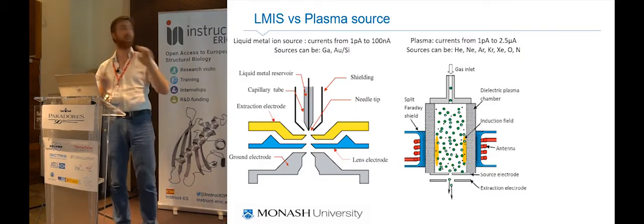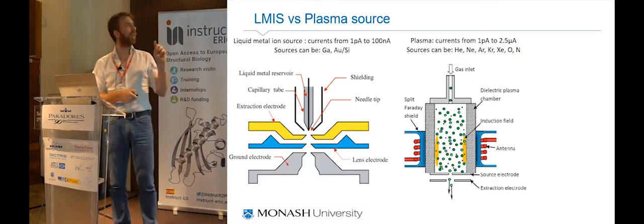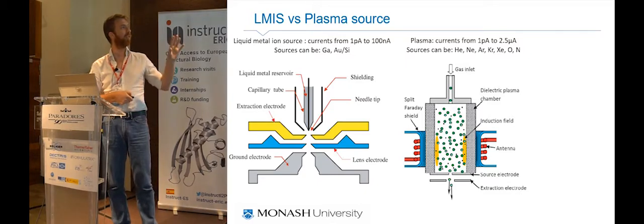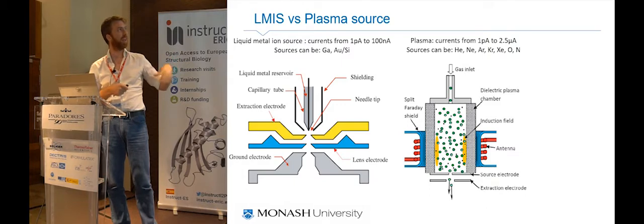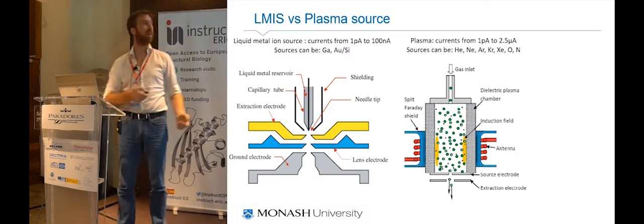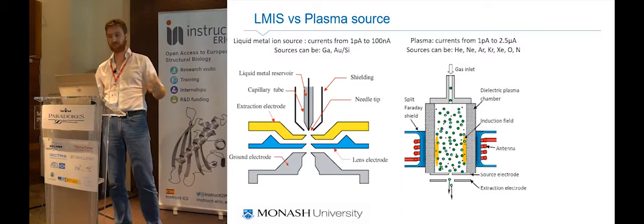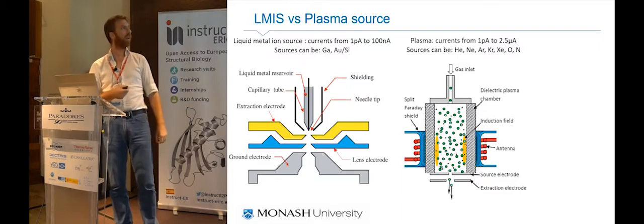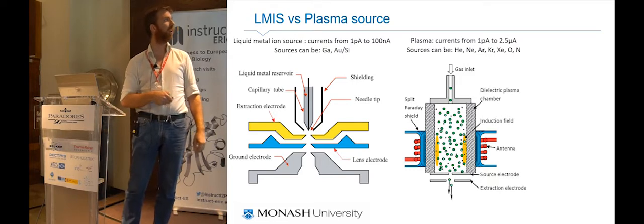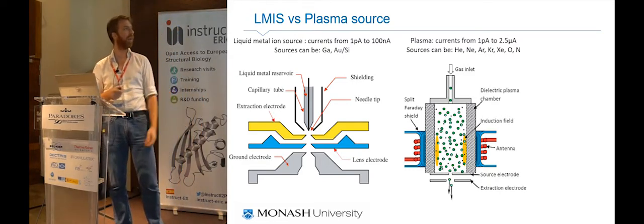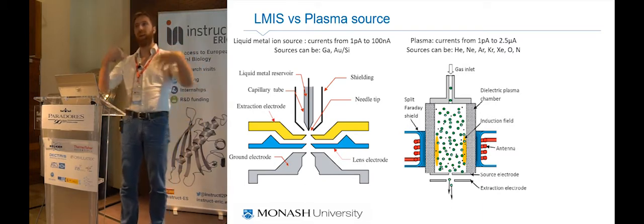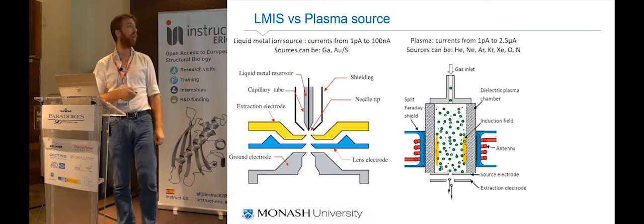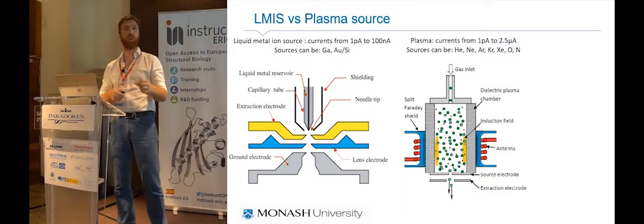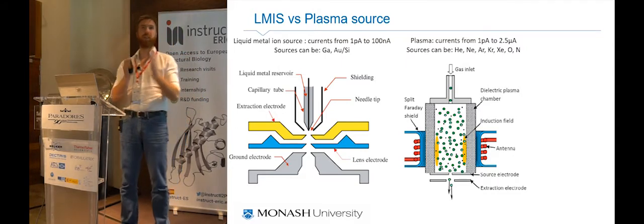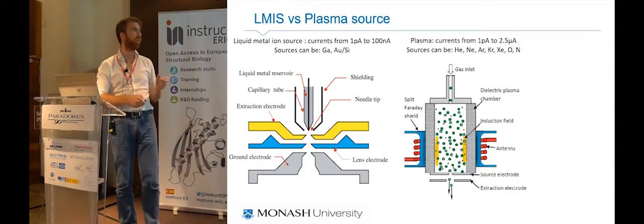First of all, you have this source, which is a leaky vacuum chamber. You leak into the chamber whatever gas you like. You apply a radio frequency, and that turns your atoms into a plasma. They will be highly energized, and then you use an electrical field again to extract your ions. The main difference here is that what comes out of this orifice, which is your source, is a collimated beam, and the size of your source will be limited by how small this orifice can be.